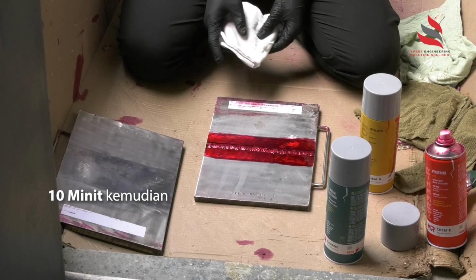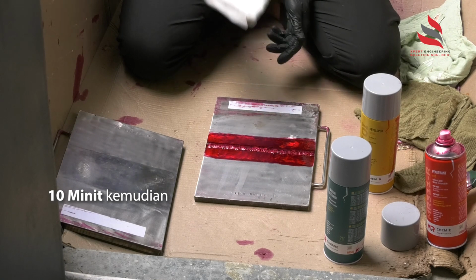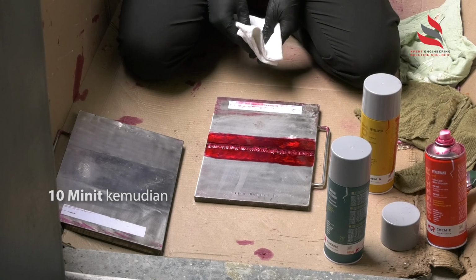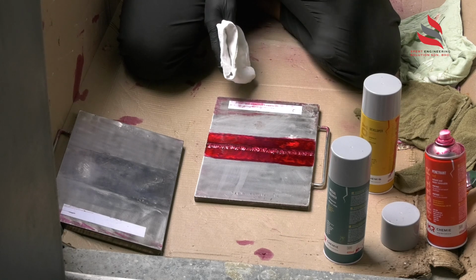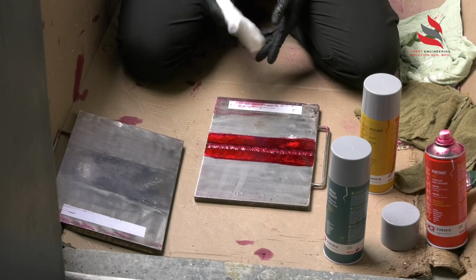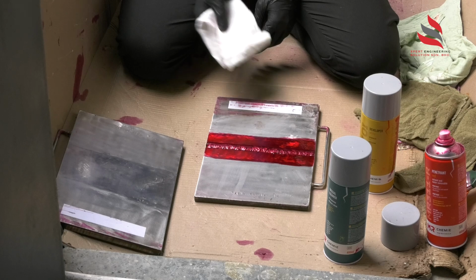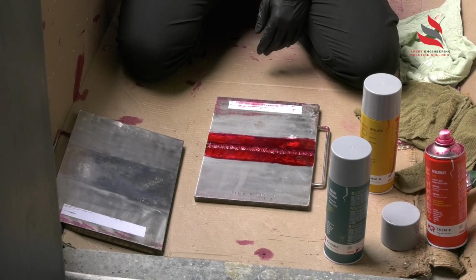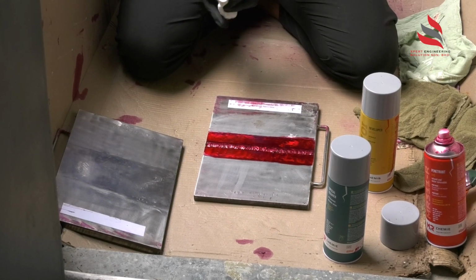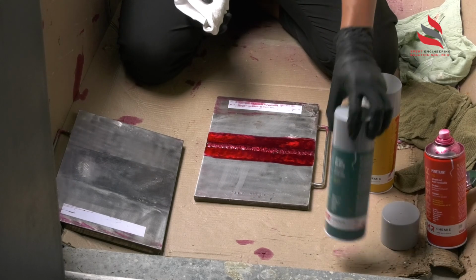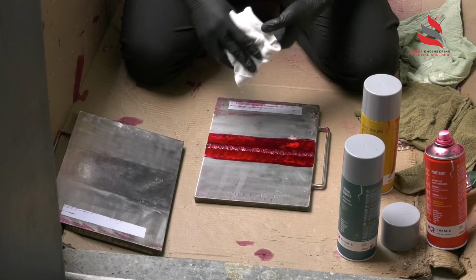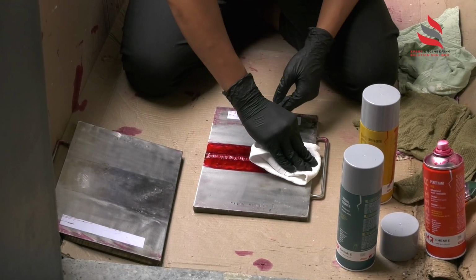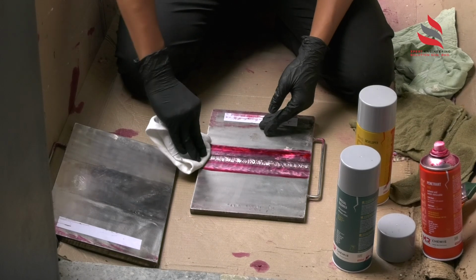After the 10 or 15 minutes of penetrant dwell time, we need to remove the excess penetrant. We use dry cloths first before we spray the cleaner onto the cloths. So we just wipe off the excess penetrant.